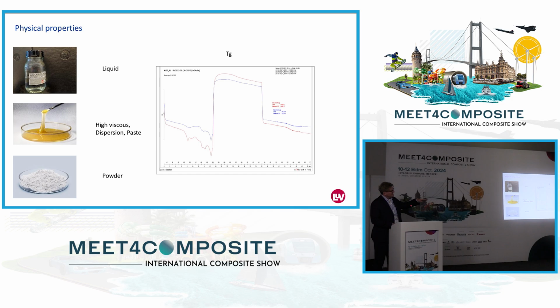What you see on the right side is a typical DSC. What you want is not to have a negative effect on your glass transition temperature. You will never achieve that, that's for sure. Your glass transition temperature will always go down, because if you add 10, 15, 20 parts of a flame retardant in your composite system, you have a different system. You have a different resin, that's for sure.